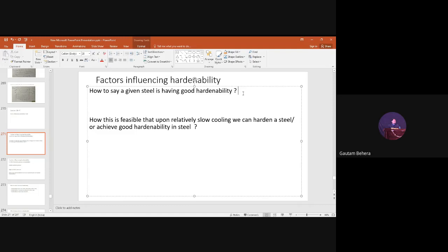You have to check the microstructure starting from the surface to the center. You can make many cross sections, you can cut it into many pieces, and take sections from different portions starting from the surface, then at the intermediate portions, then to the center portions, and check whether martensite has formed everywhere or not. If martensite has formed on the surface, in the intermediate portions also, and at the center also, that means I can say the steel you have received from me has good hardenability. It is showing good hardenability characteristics.